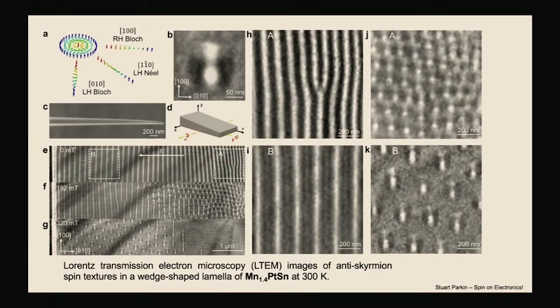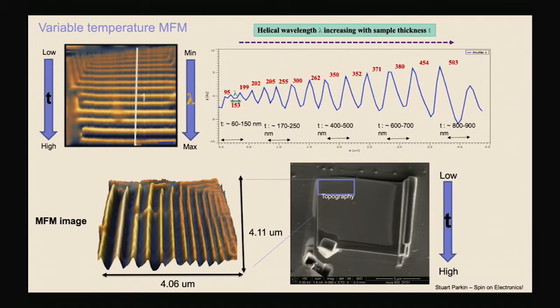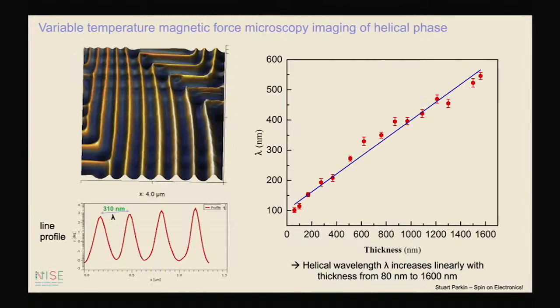So I'm running out of time, so I'll just show you. In Lorentz, we can only go up to about 400 nanometers, but using magnetic force microscopy as a function of temperature, we can make wedges which go up to thicker distances, and then it's even more dramatic. This is a profile of the magnetization in the helical phase, and you can see the period is varying from 95 nanometers at one end, the thin end, to half a micron at the thicker end, and it's even more dramatic. This shows you just a summary.